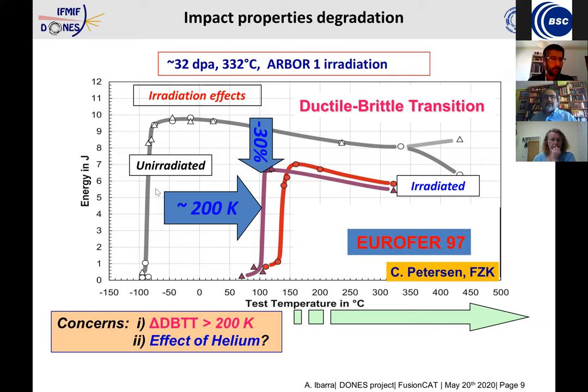And you can see it's a very good material because the transition is below room temperature, and it allows us to build a component that is working in ductile regime in all cases. When we irradiate this material, this transition moves to high temperature. As you can see, it moves a few hundred degrees centigrade. It is not a small movement. It goes from minus 100 to over 100 or 150. And of course, that means that the material cannot work in this temperature range. It must always work at temperatures significantly higher than this.